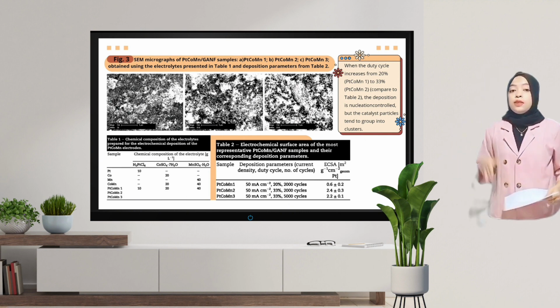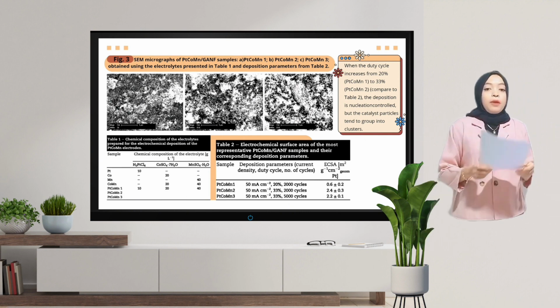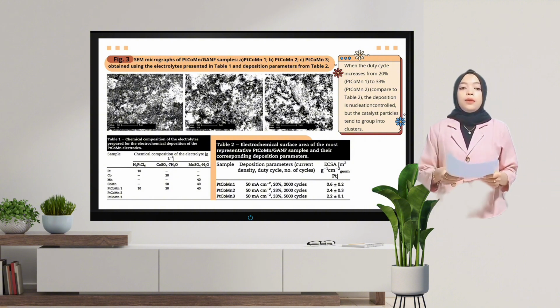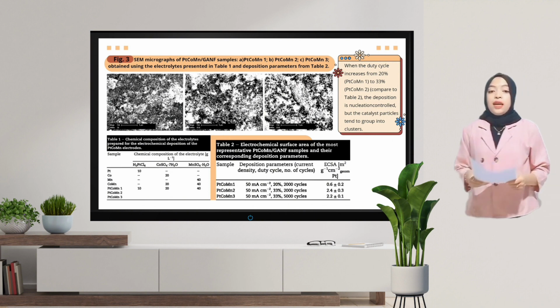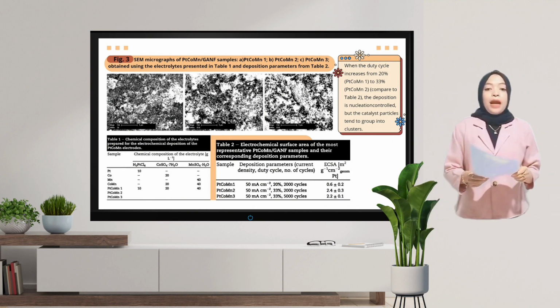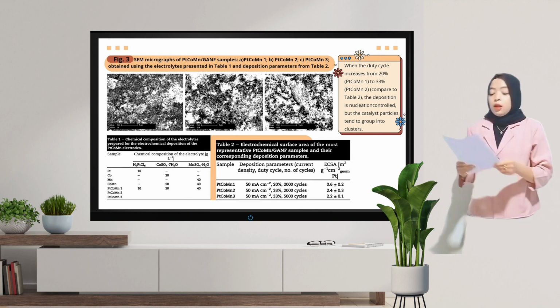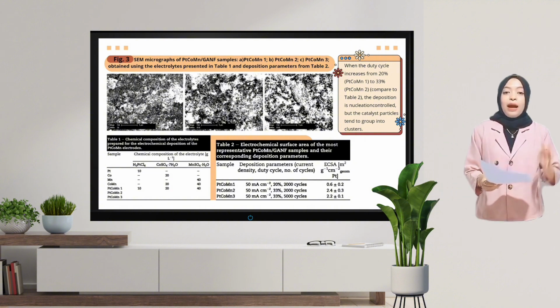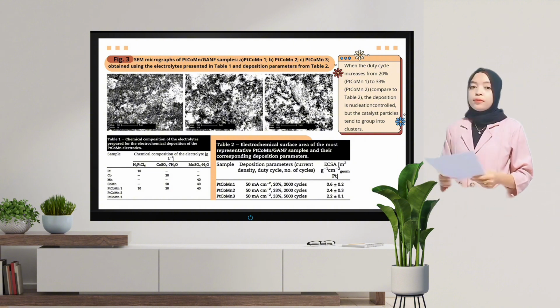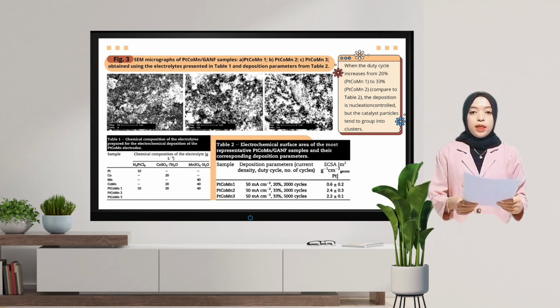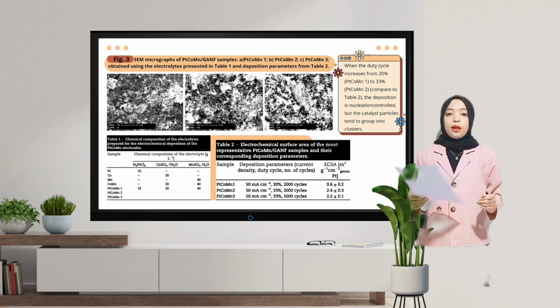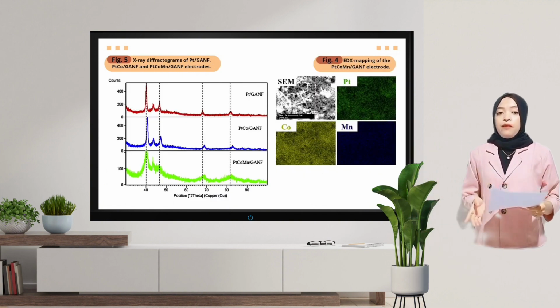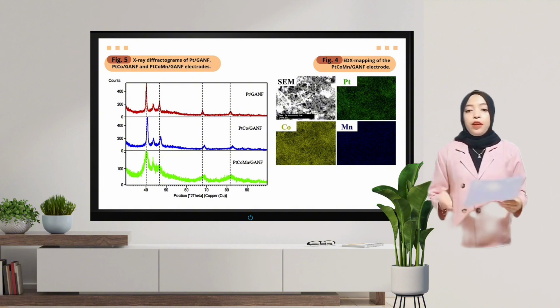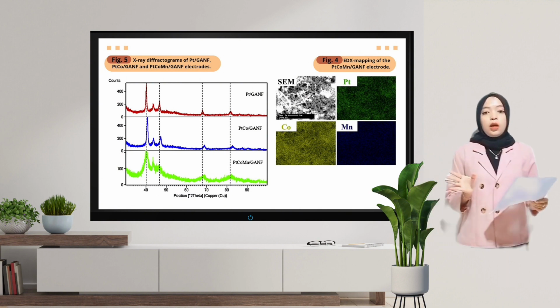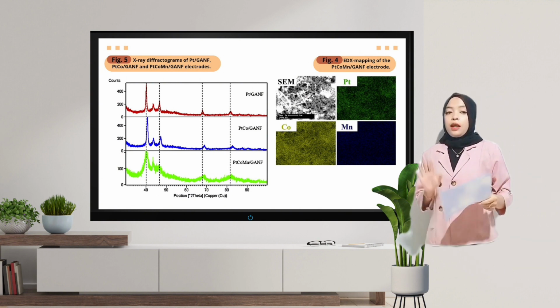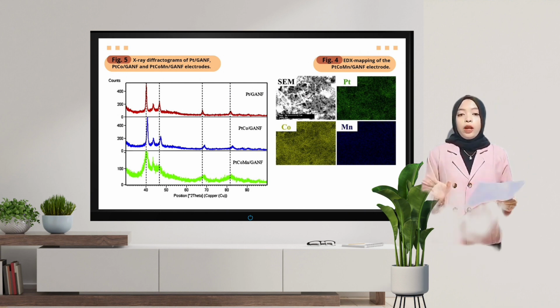The SEM micrograph presented in Figure 3 reveals a homogeneous distribution of the nanometric size catalyst particles for all the electrodes. When the duty cycle increases from 20% (PtCoMn 1) to 33% (PtCoMn 2), compared to Table 2, the deposition is nucleation controlled, but the catalyst particles tend to group into clusters. The number of cycles generally affects the amount of catalyst deposit on the graphite support system, but the particles also have a tendency to agglomerate into larger clusters, which significantly negatively affects the final ECSA value of the electrodes.